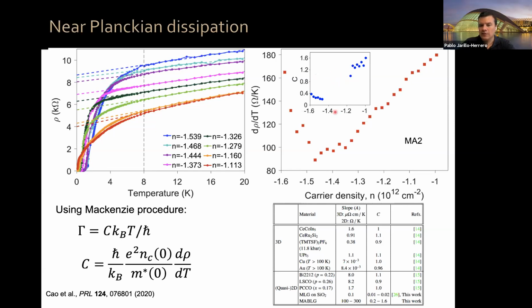Around the correlated insulator state for 2 holes, so -2 plus delta, what we see is values of the coefficient C or alpha, if you want, which are within 50% of 1. For extra holes, at -2 minus delta, this coefficient varies between 0.25 and 0.4, something like that. So it's certainly within a factor of 3 or so of this value of 1, this Planckian scattering rate. And this is what we have for graphene.